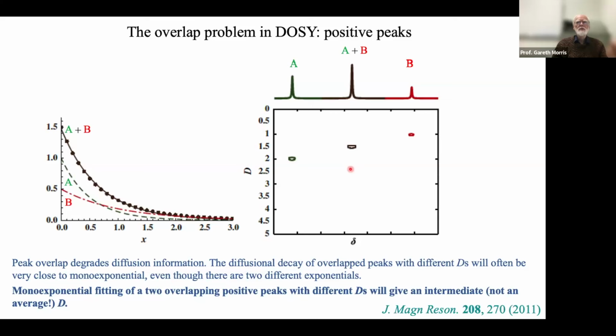So whenever we look at a basic DOSY spectrum, we always have at the back of our minds the possibility that any given peak is appearing where it does in the spectrum, not because that's the diffusion coefficient of the molecule that gave rise to the peak, but because that's a compromise between the diffusion coefficients of the two or more molecules that contributed signal to that peak. So mono-exponential fitting of two overlapping positive peaks with different Ds gives us an intermediate D. You'll occasionally see people say that it gives you an average diffusion coefficient. Think about the process, you can see that's obviously wrong.